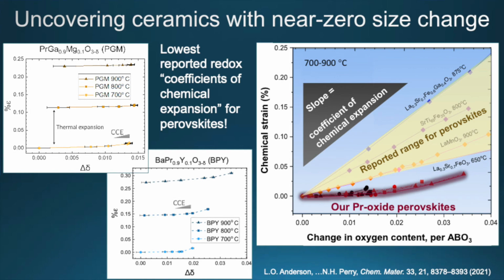So the property we care about here is the slope. This is something called a coefficient of chemical expansion. Fancy language just to say how much is it expanding or contracting as it breathes. Our materials have a much, much, much lower slope. These are record-breaking. They're up to 500% less than what's reported. So that's really cool. There's a lot of complicated reasons for why these work that I won't go into right now. But it has to do with where the charge is in the material.